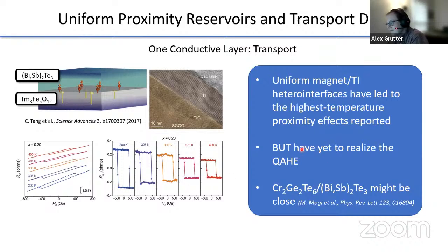But on the other hand, there's no, at least as far as I'm aware, maybe something really recent came out, but they have yet to realize the quantum anomalous Hall effect in these systems. And as just a small side note, there is one report that might be quite close, and that's chrome germanium telluride interface with bismuth antimony telluride. They don't quite achieve quantization, but the anomalous Hall effect is very, very large. And so it might be close.